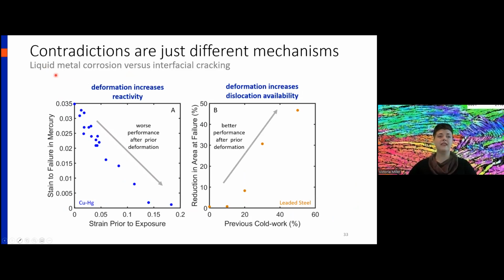So when we look at liquid metal corrosion versus interfacial cracking, this is the same strain prior to exposure and some measure of ductility. In the copper mercury case, deformation increases the reactivity, so you get worse performance after prior deformation. Whereas in the leaded steel, deformation increases dislocation availability, so you get better performance after prior deformation. That's the difference between something like liquid metal corrosion, where reactivity is your primary concern, versus interfacial cracking, where dislocation availability is your primary concern.